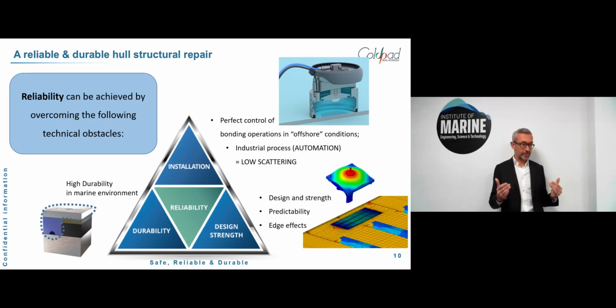We've made hundreds of tests and hundreds of numerical simulations to make sure that we understand how it behaves in order to optimize the performance. So to summarize, you have to control installation and avoid humidity, durability by avoiding the moisture from reaching the bond line, and last but not least, master the strength to avoid what we call edge effects, because usually the stress will be concentrated close to the singularity, typically at the edges of your assembly.